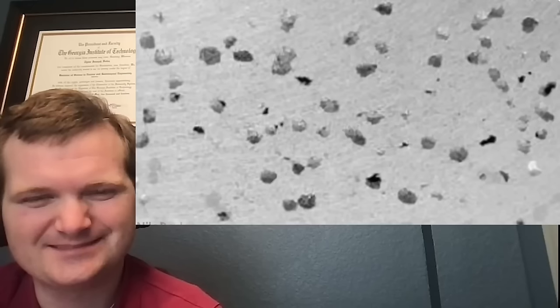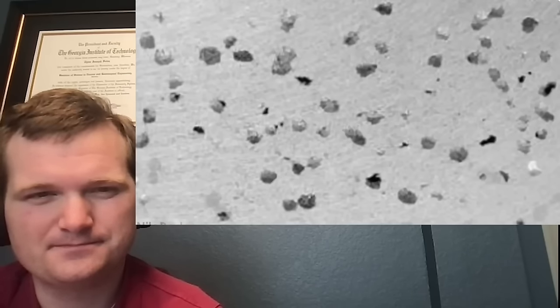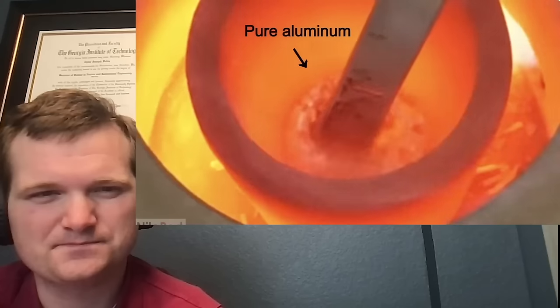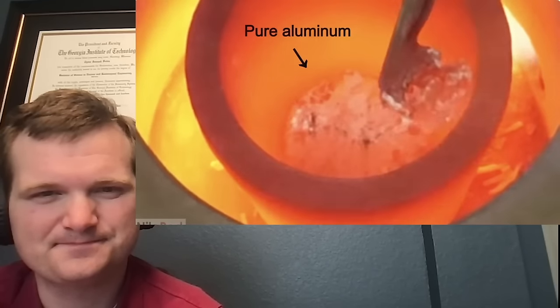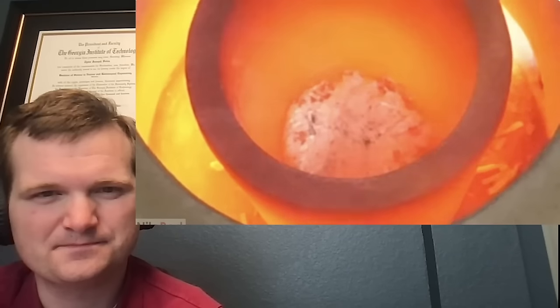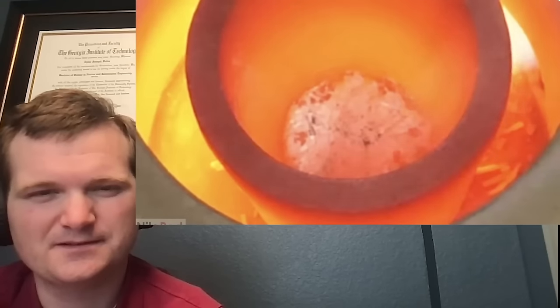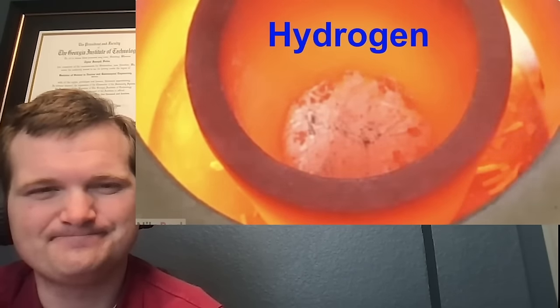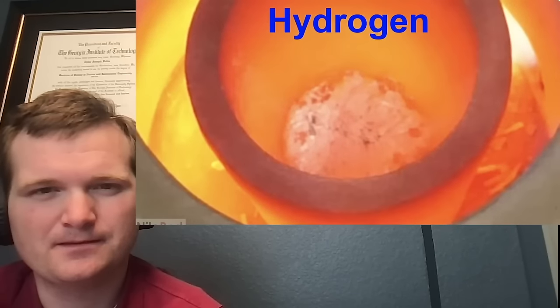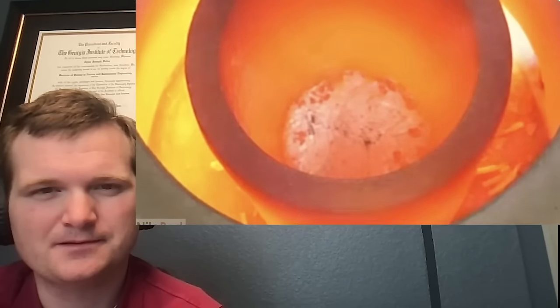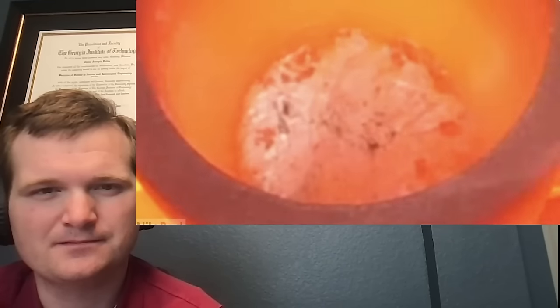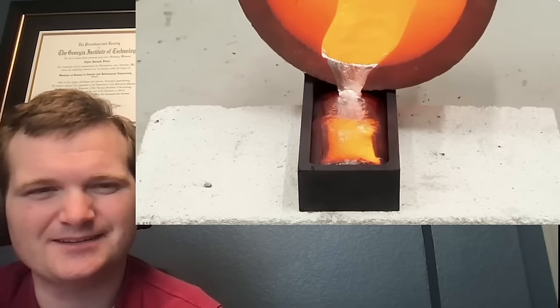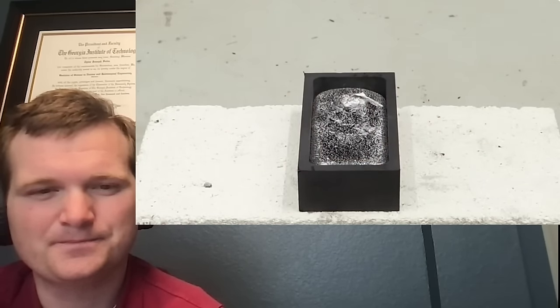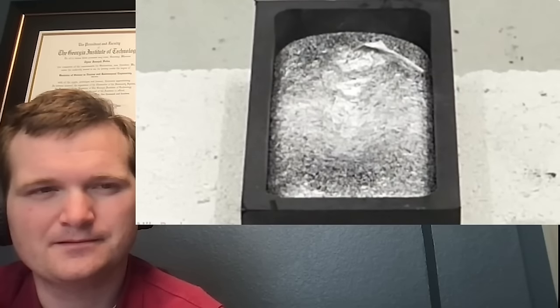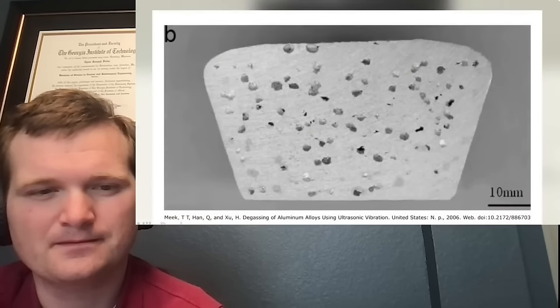All of the dark spots were small holes, just like what I was seeing with the purple gold, and apparently, this was mostly just caused by moisture in the air. This is because when aluminum is molten, it's able to react with the moisture, which then causes it to form some of those crusty oxides like we saw before, as well as some hydrogen gas. I always kind of assumed that all of this hydrogen then kind of just floated away, but apparently, a lot of it actually gets dissolved into the molten aluminum. Then, as the aluminum cools, the solubility of the hydrogen slowly decreases, and right around the time that the aluminum is solidifying, it all gets kicked out as a bunch of bubbles.